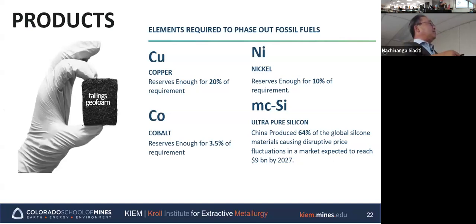Other than geofoam from the tailings, we can recover copper. The amount of copper that we can recover from tailings is about 20% of the requirement. Global copper production is about 22 million tons, so we can produce an additional 20% out of it. For nickel, we can produce about 10%. And cobalt is a little lower, only 3.5% additional metal production by reprocessing.